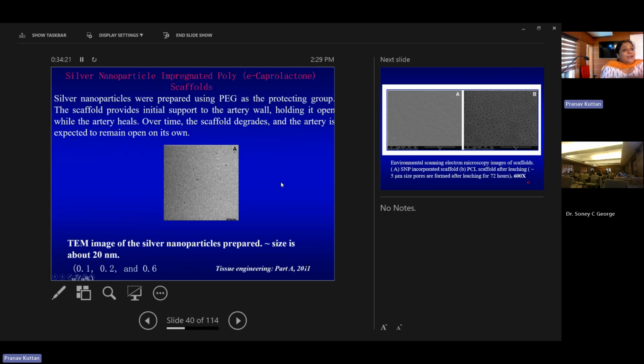so that we don't have to do one more surgery to remove that vascular scaffold. One difficulty found with this kind of polymer scaffold is that infection can happen at that point. So that was the reason why we thought of developing silver nanoparticle incorporated vascular scaffolds, so that you don't have to provide an extra antibacterial agent. In this case, silver protected with polyethylene glycol was chosen. You will know silver generally cannot stay as such, it needs a protecting group to stabilize. Otherwise, since this nanoparticle has a large surface area, it will not be stable.